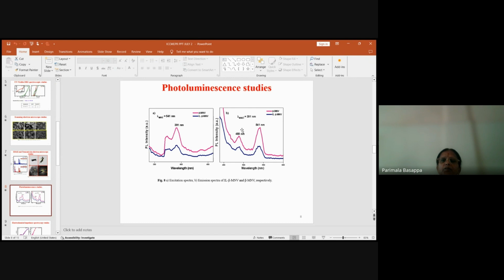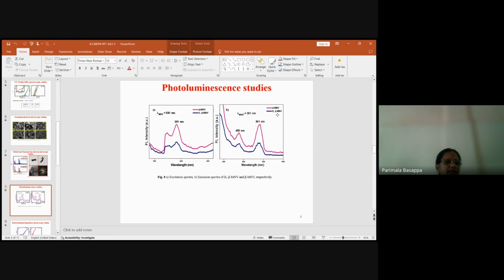This first one shows a higher PL intensity than the ionic liquid beta manganese vanadate, because in the first case there is greater charge carrier recombination. The charge separation in the ionic liquid sample may enhance the photocatalytic activity. So in the beta MNV there is more recombination, whereas in the case of ionic liquid beta MNV there is charge separation. So it enhances the catalytic properties.